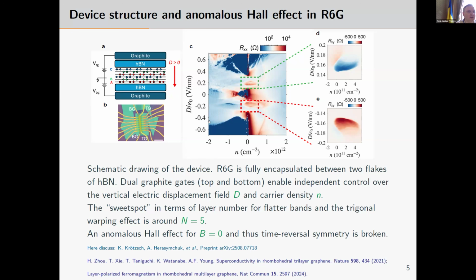And here is this color plot. Here the carrier density n is changed, and the gate voltage, and you see this is the diagonal resistance of the sample. The experimentalists this time concentrated on these areas of low carrier density, and the insets show Hall conductivity measured. You see already something interesting: those measurements are done in zero magnetic field, and apparently you see a sign of anomalous Hall effect. It's already interesting because it shows that there is spontaneous time reversal symmetry breaking in this system. This is the reason why it's interesting.